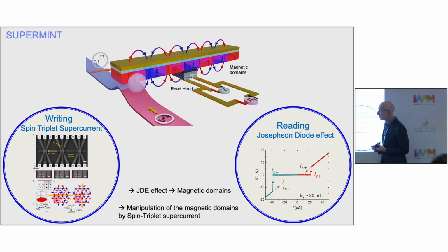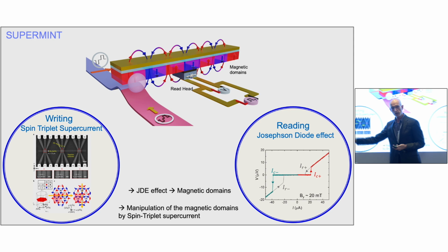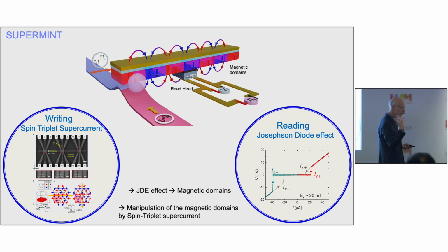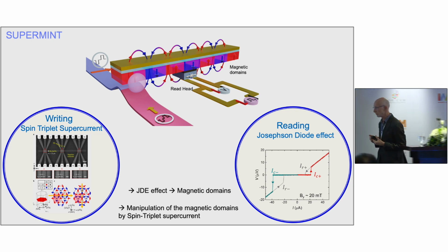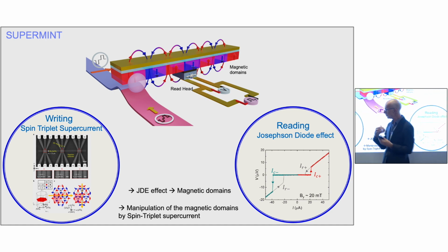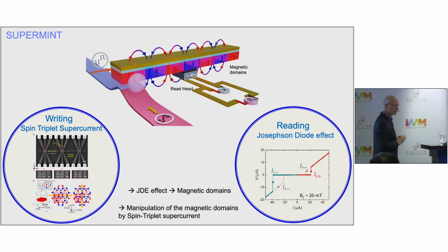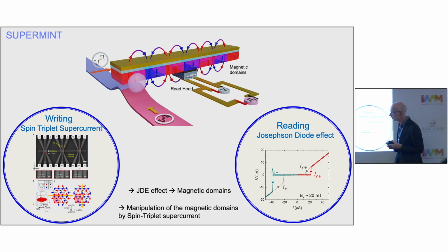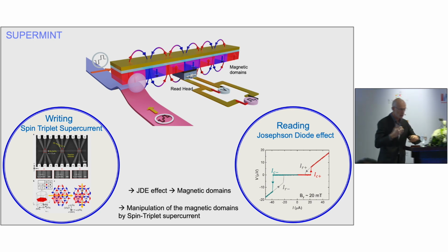And so I want to briefly mention that the same chiral antiferromagnet that I've been discussing is actually an inhomogeneous magnetic system. And we've recently demonstrated, for the first time, that by injection from niobium, you can generate spin-triplet proximity-induced Cooper pairs that are long-lived and will move over long distances. We published this just a few months ago in Nature Materials. But it's the same material, manganese-3 germanium. So these systems are super interesting for this possibility.